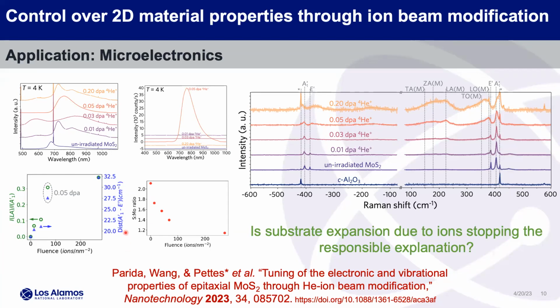If we plot the distance between these two modes, the E and the A mode, you can think of it as a measure of strain state in the material. This matches up pretty well, with the exception of an outlier at 0.05 DPA, which also aligns with this huge shift we see in photoluminescence intensity. This is all at 4 Kelvin, well, nominal 4 Kelvin is probably really 7 Kelvin. But that's a nice observational trend that we saw.